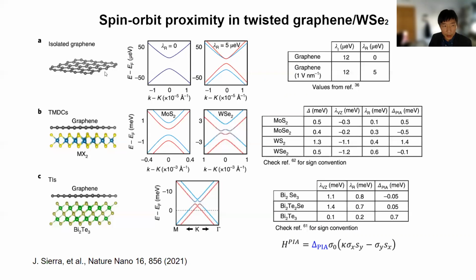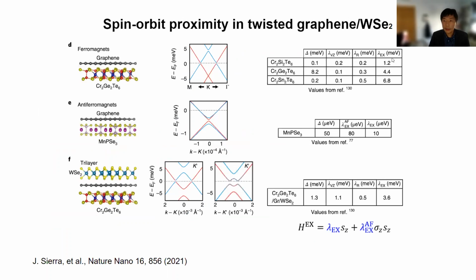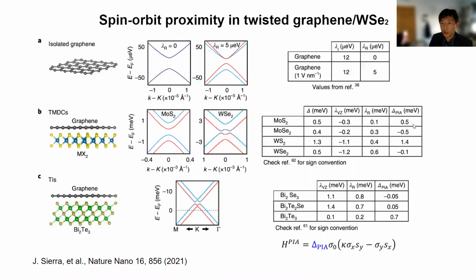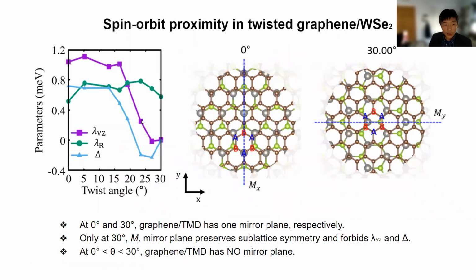Here is a summary of the size of those parameters for different systems that have been studied in the literature. Typically that effect, as I mentioned, is very small, of order of milli electron volts. First, let's look at two particular angles, a 0 degrees case and a 30 degrees case. We see that in these two cases, there is a line of symmetry. But if you go to other angles apart from 0 and 30 degrees, there is no mirror symmetry in those systems.